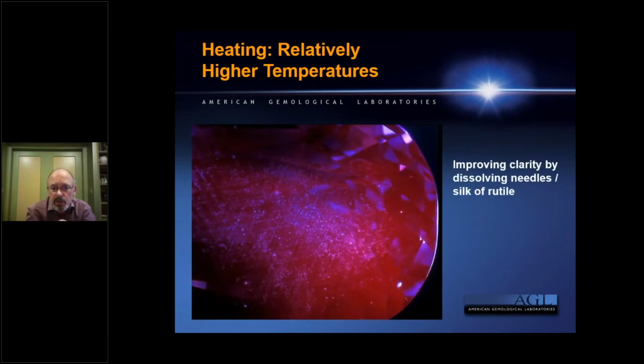So here's an example of a stone. This stone is actually in kind of the midway process of dissolving the rutile silk. You can see actually the threefold symmetry axis, which is still existing here. They're no longer needles, but stringers of particles. As you continue to heat this stone, for a longer period of time or at higher temperatures, you'll be able to draw all of this titanium, rutile is titanium oxide, you're going to be able to pull all of this titanium back into the lattice so that the rutile completely disappears, significantly improving the transparency of stones.